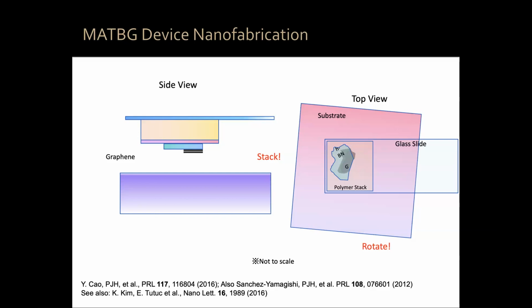So we're doing this under a microscope. You pick up this flake with the HBN, and then you know exactly what's the relative angle between this and this, because you didn't rotate in between. So now we literally do that thing. We rotate 1.1 degrees, we translate, and we put it on top. It's not like you take one piece and then the next day a piece from another place. No, we have very rigid positioners. When we do this thing, the angle doesn't change.